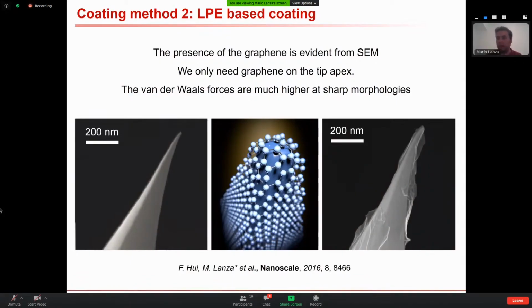And it's not a matter of luck, because the point is that the graphene doesn't attach everywhere, but the sharp shape of the tip increases the van der Waals attraction. Van der Waals attractions are much higher in sharp geometries, and for this reason we observe that the probability of getting graphene attached to the sharp apex of the tips is much higher than in any other location. Most of the tips that we apply, above 90%, have graphene on the apex. However, there is one critical parameter that Dr. Fei Hui tuned very well, which is the density of graphene in the solution. If you put too little graphene in the solution, you will not get coated tips. If you put too much, you will get a big amount of flakes on the apex that will not make your tip suitable for AFM measurements. So what you are seeing here is the optimal coating.